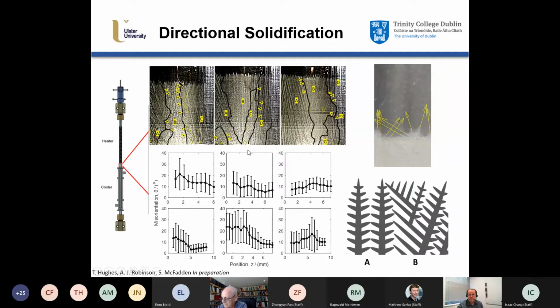recall that there's the Walton-Chalmers orientation mechanism that says that there's a preferred orientation for crystal growth, directional crystal growth, if it's columnar. And you see here the example at the bottom middle is classic Walton-Chalmers. So you see the orientation initially, on average, is quite large, but then it converges down to a preferred orientation of 0, in other words, growing in the vertical direction. And you also see the error bars are the spread of the orientation measurements, and they're also reducing. So in that case, you do see classic Walton-Chalmers behavior.